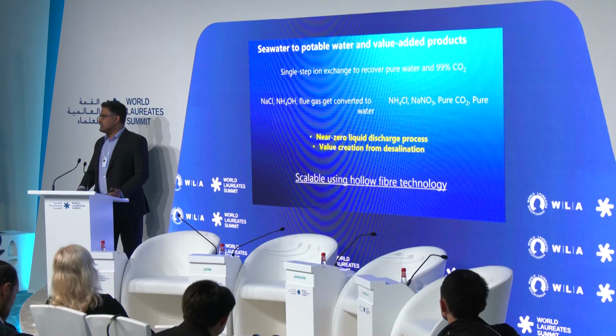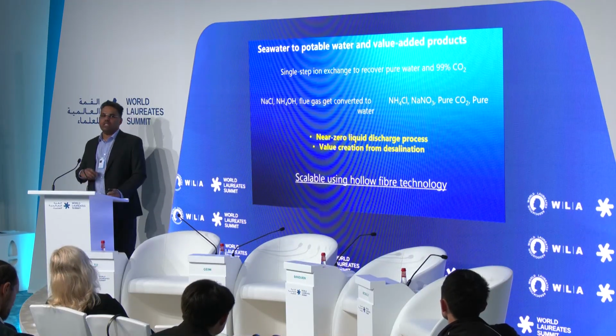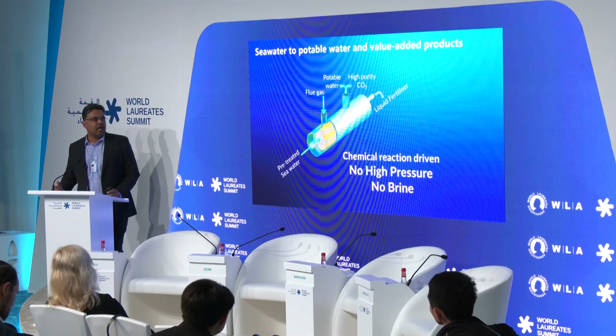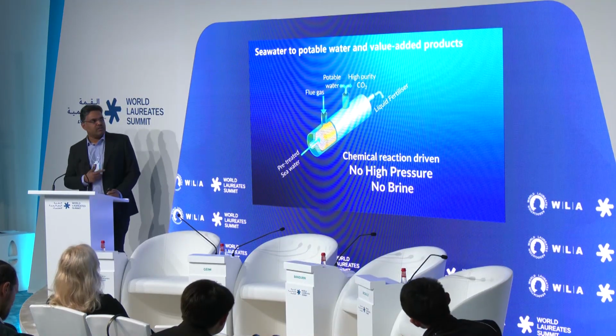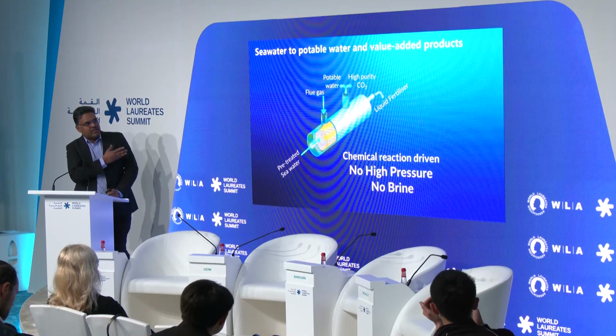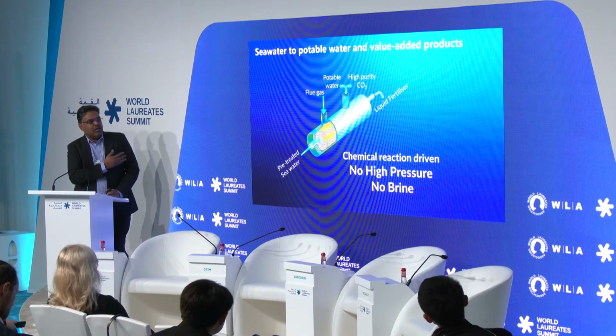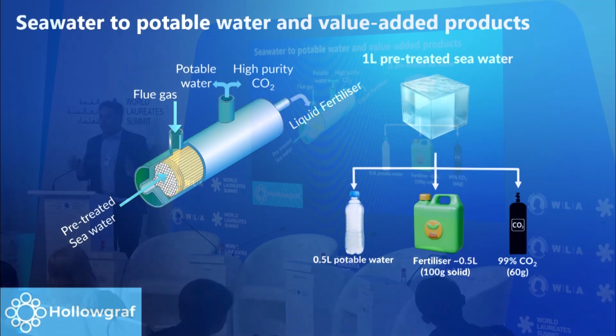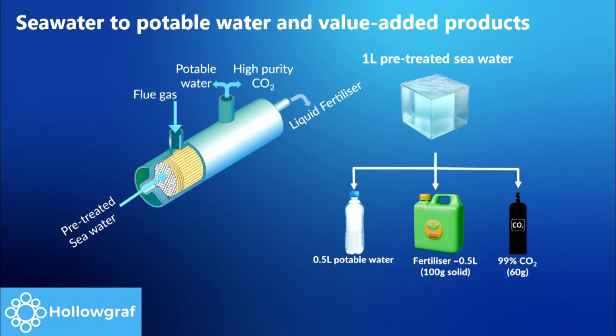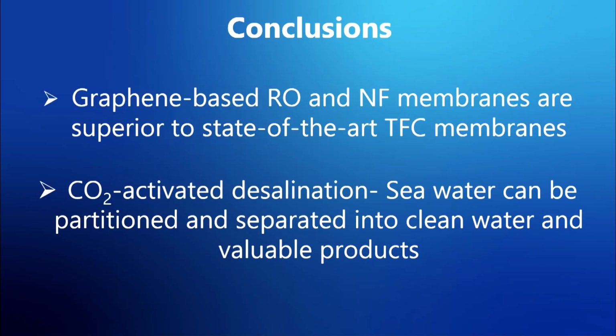And it is also scalable by using hollow fiber membranes. Now, the state-of-the-art RO process uses spiral wound membranes, whereas here we are using hollow fiber. This is a simple process with no external pressure and so on. Just for comparison, if you take 1 liter of pre-treated seawater, during this process what we generate is half a liter of potable water, and half a liter of liquid fertilizers and pure CO2. That is the whole process, and we are now commercializing this technology through a spin-out from the university called Hollowgraf Limited. With that, I conclude.